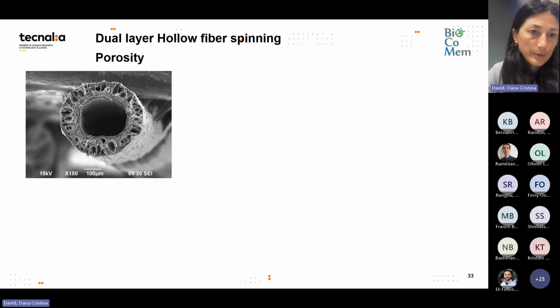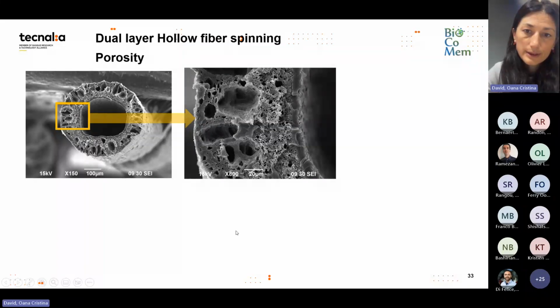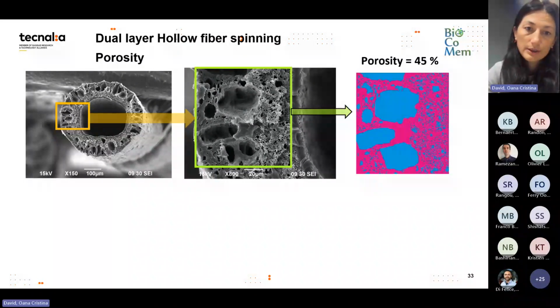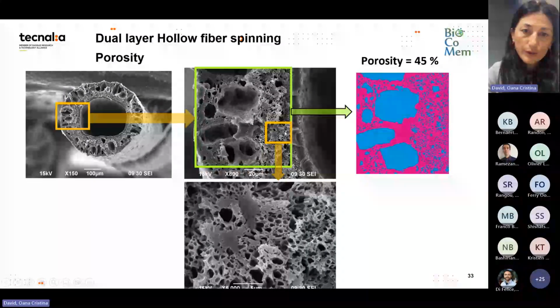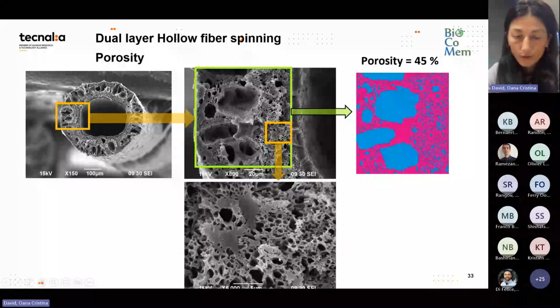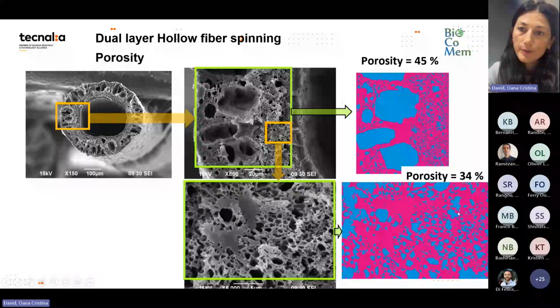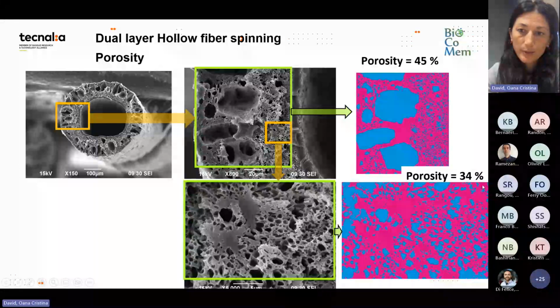These are the membranes shown in a SEM micrograph. So we see the inner layer dense. This is the selective part. And this is the porous part of the outer layer. And we tried to determine the porosity in the cross section, which was about 45% if we take the entire cross section. Here we have these big pores which are not desired, so we still have to improve that part of the fibers. And then if we look here at this nice part, we would like to have this kind of interconnected pores all over the cross section. Here we have a porosity of 34%, and this is done by image analysis.